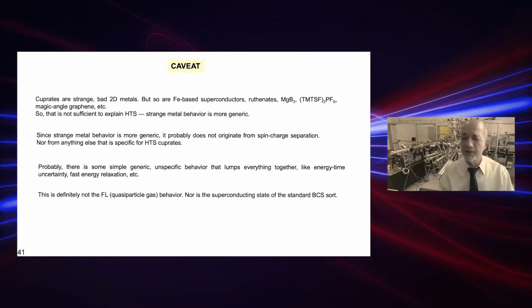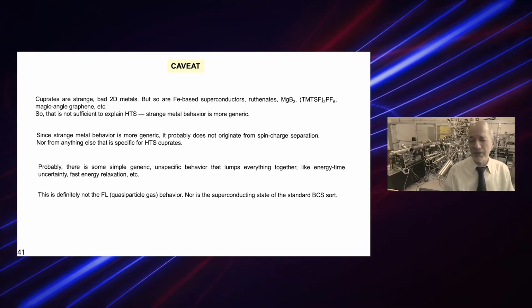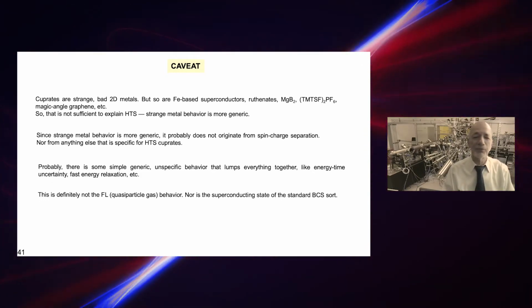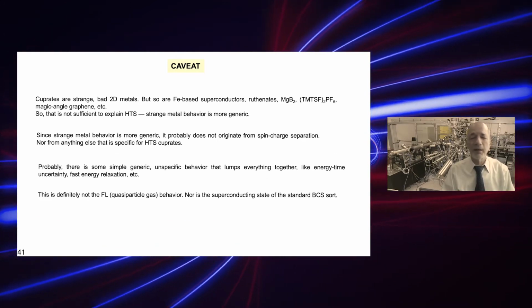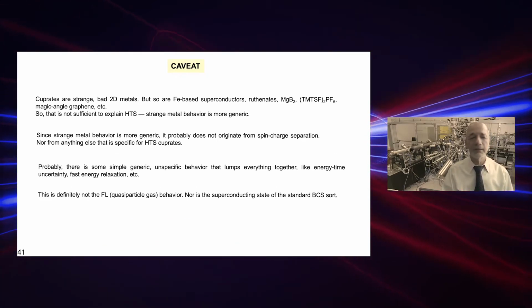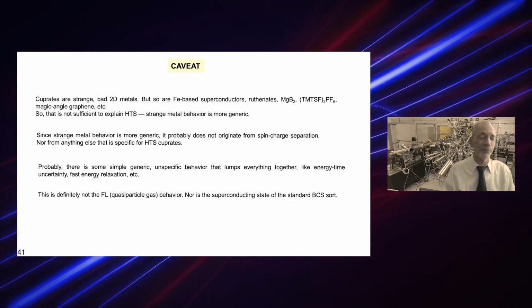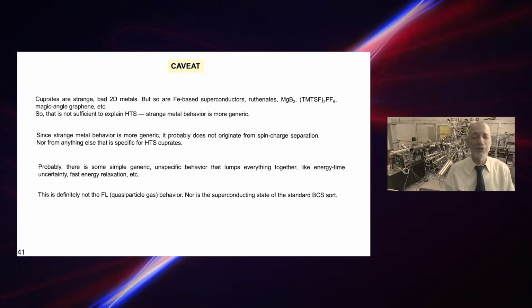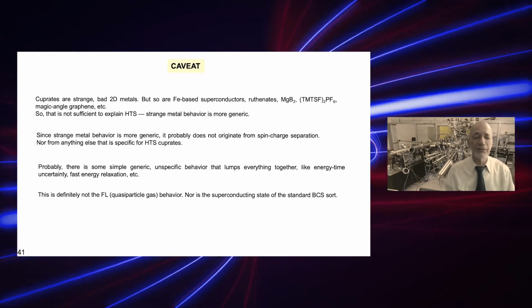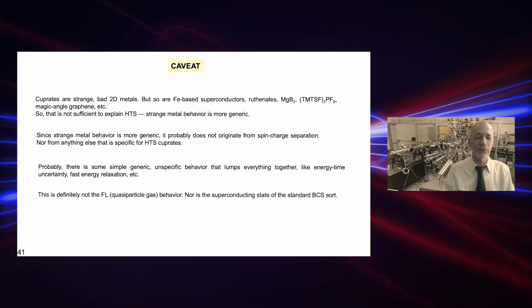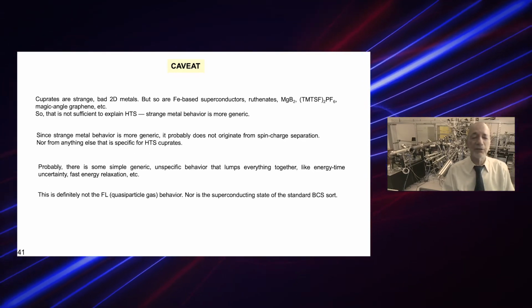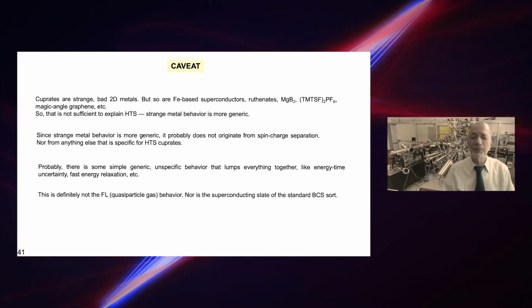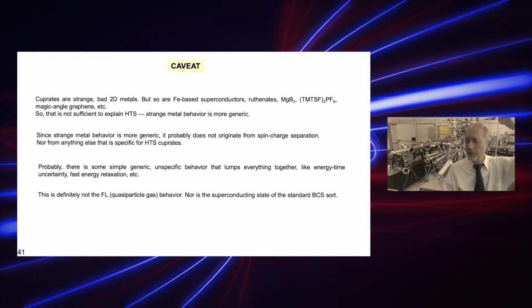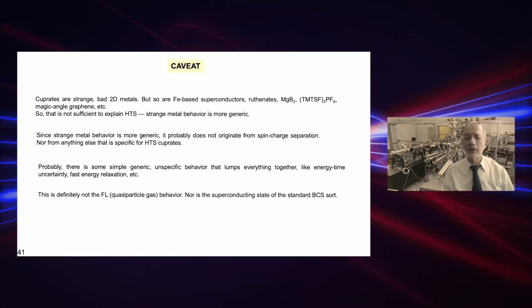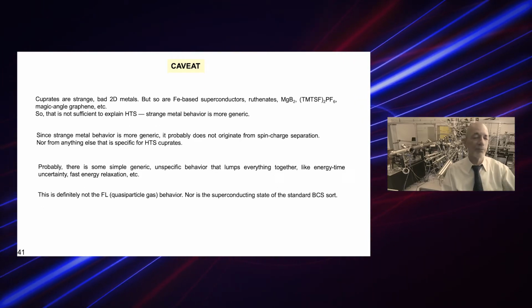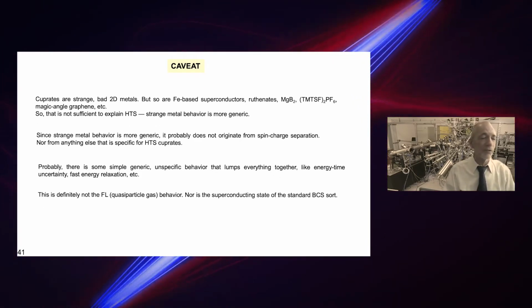It could be, for example, arising just from the Heisenberg uncertainty relation between energy and time, and the fact that we are at the limit of ultra-fast, essentially instantaneous energy relaxation and hydrodynamization, as Jan Zaanen would argue. In any case, this is not quasi-particle gas behavior. And then by Gor'kov's tenet, it means that the superconducting state cannot be of the BCS sort.